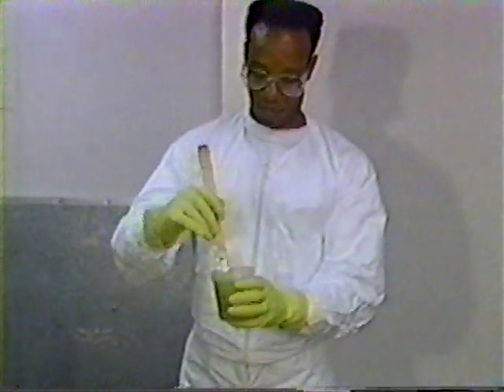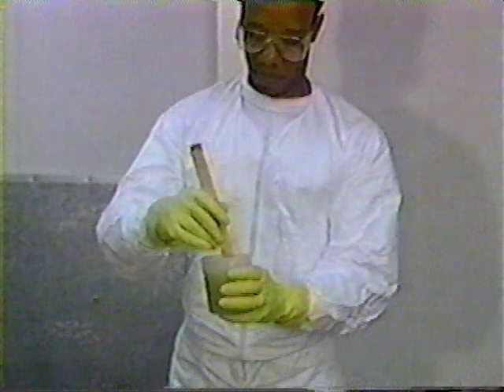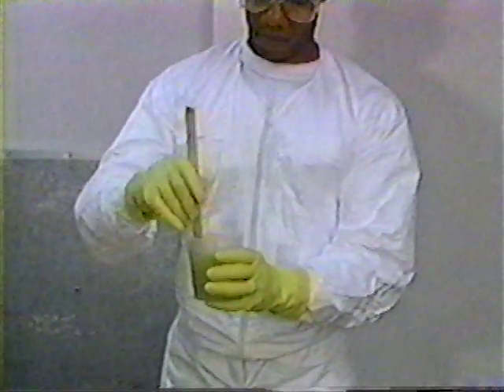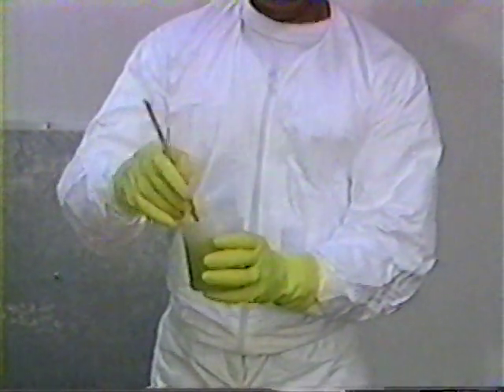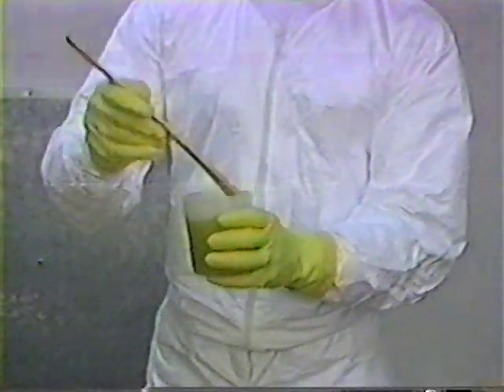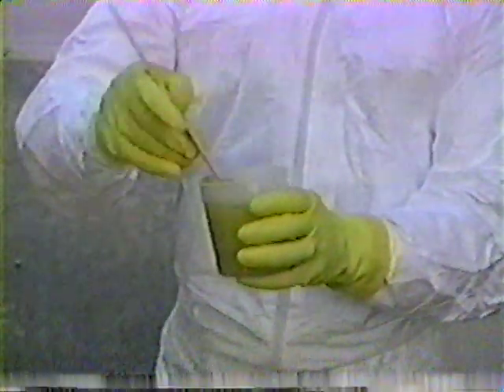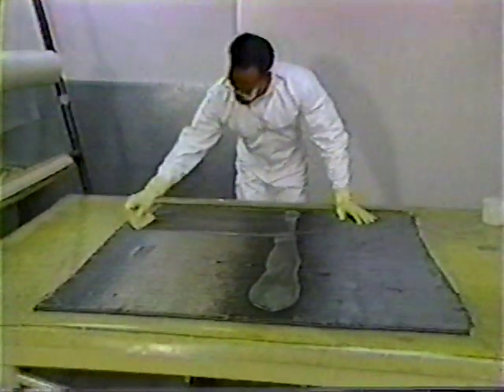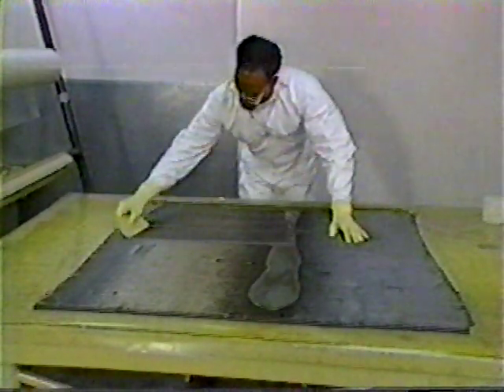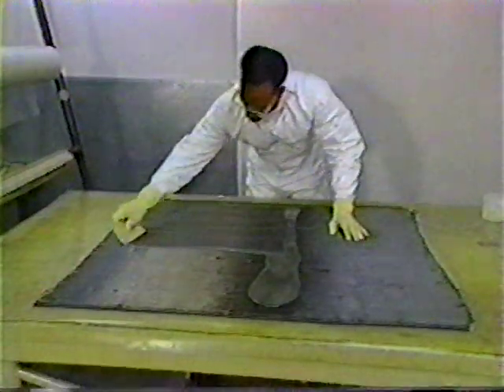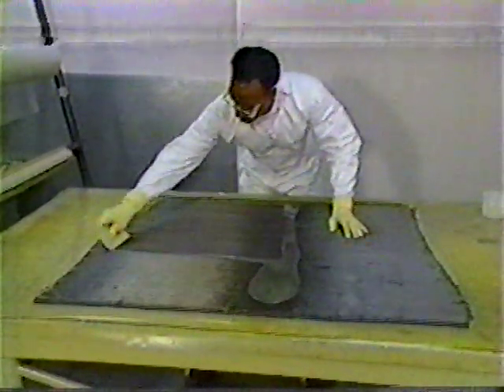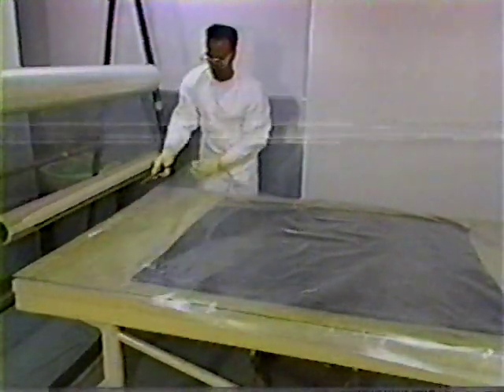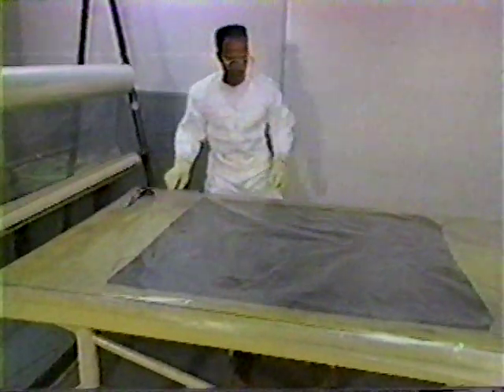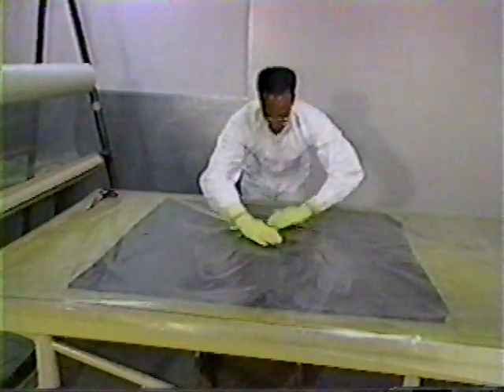After the warp orientation has been determined, mix the resin according to manufacturer's instructions in a well-ventilated area, making certain to wear the appropriate personal protective equipment. Next, apply resin to the graphite, working the resin into the weave of the material until it is thoroughly saturated. Then, cover this with a second sheet of non-porous parting film and smooth out all the wrinkles.